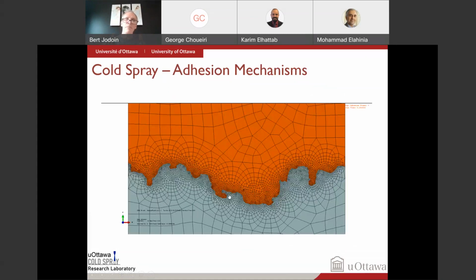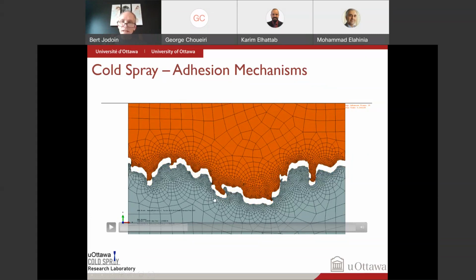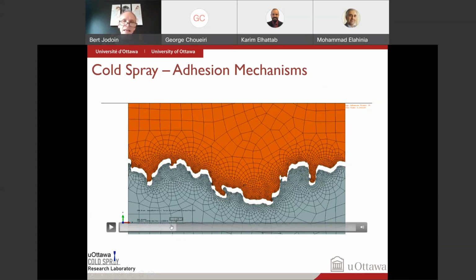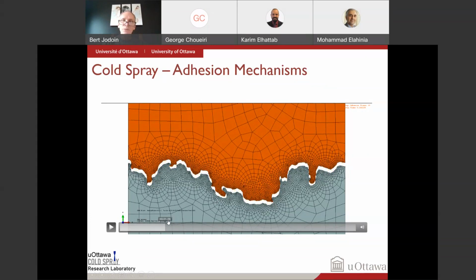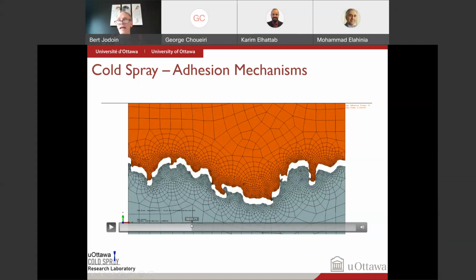So here I have a physical model. What we've done is we've scanned this, imported it and meshed it to try to be able to predict the adhesion strength. At the bottom, you have the steel substrate that's modeled, and at the top, you have the copper coating modeled based on the cross-section of a real coating we've obtained. We've tested this for adhesion, and then we wanted to see if we can predict this using FEM. It allows you to see, when we pull on this, look at these areas here and here and here, you can see that you have these parts that will prevent the top part from easily detaching. That is mechanical anchoring. It's one of the two adhesion mechanisms, and it can be very strong. You can reach 12, 15,000 psi in adhesion strength from this mechanism.